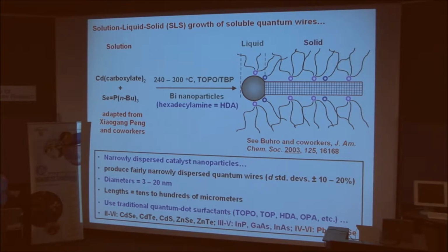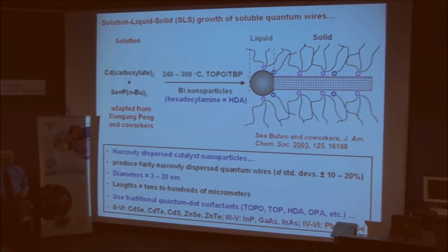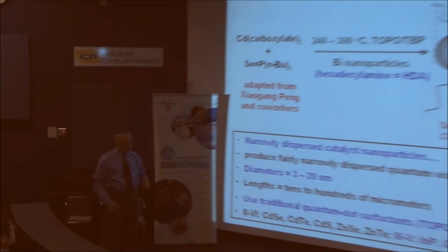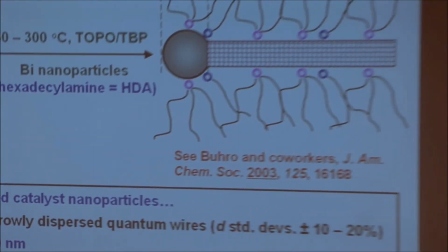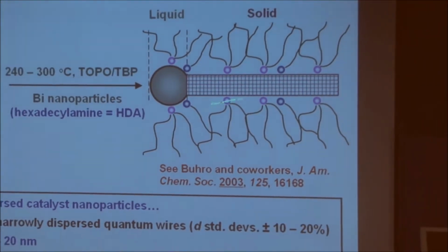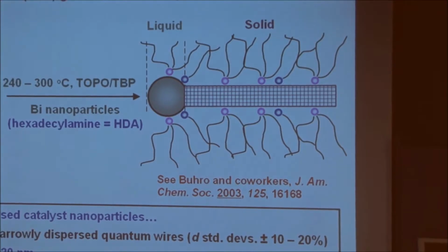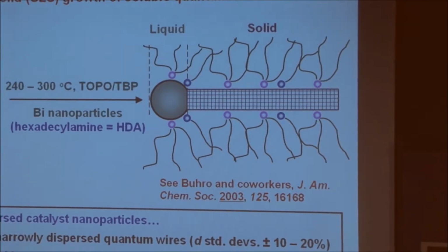This is done in solution or solution dispersion, much in the way that colloidal quantum dots are grown. In fact, we use very much the same precursors, the same kinds of solvents, the same kinds of temperature ranges, and the same kinds of surface passivating agents. But the key difference in this synthesis is that we purposely add a dispersion of nanometer-sized metallic particles that catalyze the wire growth. And so here's how it works.